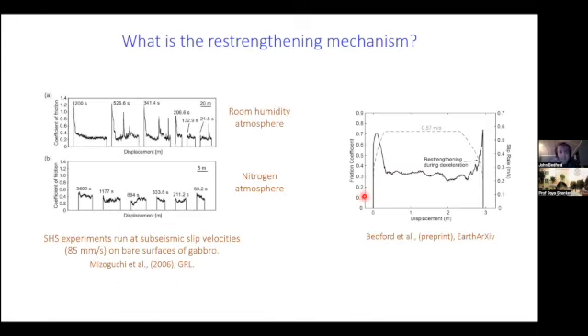And there is other evidence to suggest that chemical bonding might be responsible for rapid healing in friction experiments. So there was a study performed a few years ago by Mizoguchi et al., where they sheared bare surfaces of gabbro, so not gouge, just bare surfaces, rock to rock experiments. And they did some experiments in the room humidity conditions, and they did some experiments under nitrogen conditions. And what they found is these are slide-hold-slide slip pulses, and we see the hold time listed here. And under room humidity, we do see the strength recover and the peak strength increasing as it's been held for longer static hold periods.